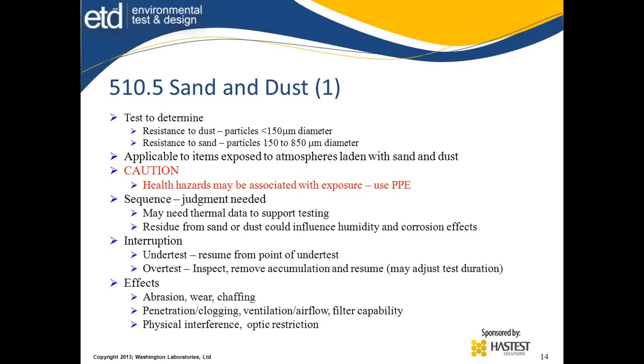The sequence, a lot of judgment is called for here. You may need the thermal test data to support the testing. Well, quite often you do. A unit is supposed to be exposed to the high temperature for operating or storage during one of the tests. If you don't know what the high storage or high operating temperature is, then how do you know how to do this test? You don't. So it's spec to operate at 55 degrees C. Well, you may see that the test only passed at 50 and they get a spec change. So you need to get the test data to know what is going to happen. You don't want to have a failure here because of a thermal issue that you weren't aware of.